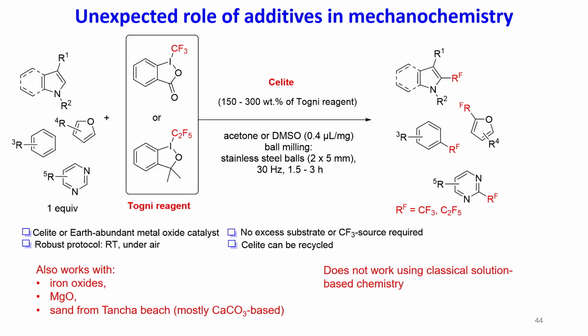So we found that with Celite, which everybody thinks is totally inert, actually is a real activator of the mechanochemical trifluoromethylation. And it only applies to mechanochemical conditions. It offers many practical advantages because Celite is cheap, and it's non-toxic, so it's very much earth abundant. It's easy to get, and it's not just Celite we had success with. We could also achieve similar results if we worked with iron oxides, also amazing activators, and even something simple like magnesium oxide. And then I told Thomas, you should go and collect some sand from the beach. So Thomas did it. He went to the beach and he collected some sample of sand.